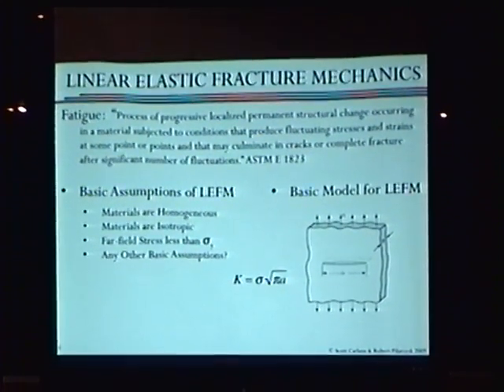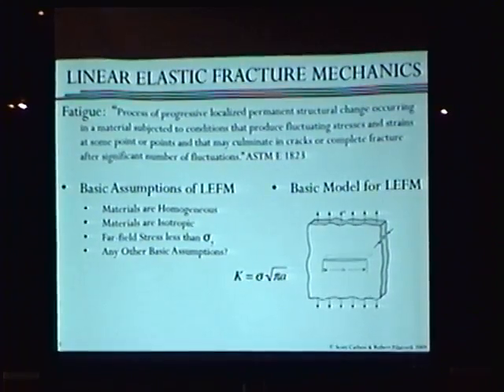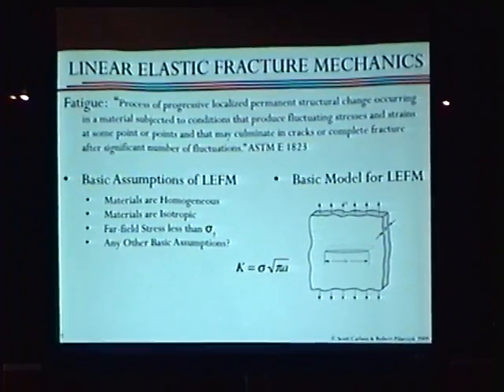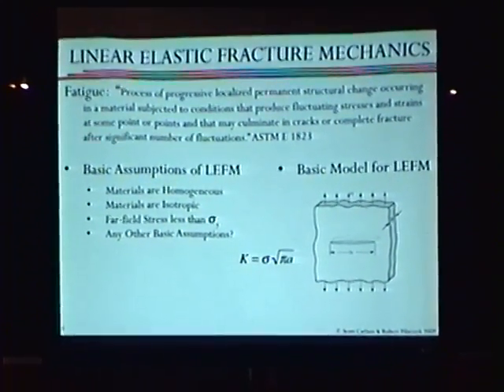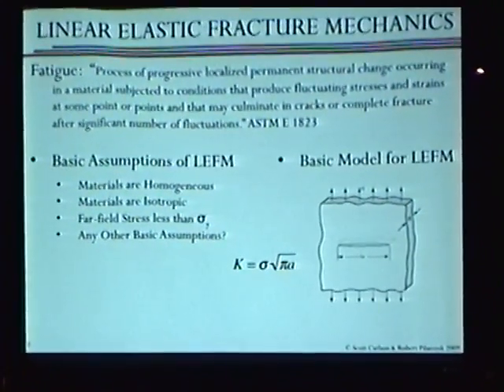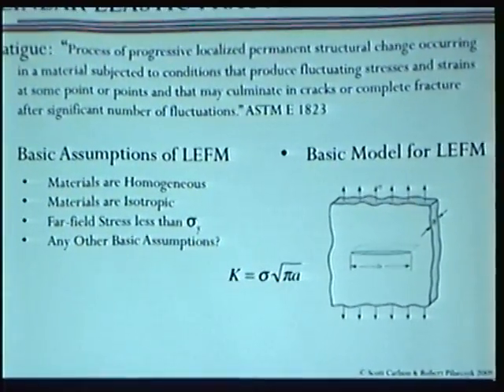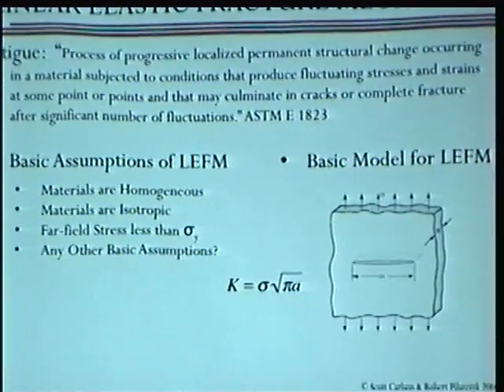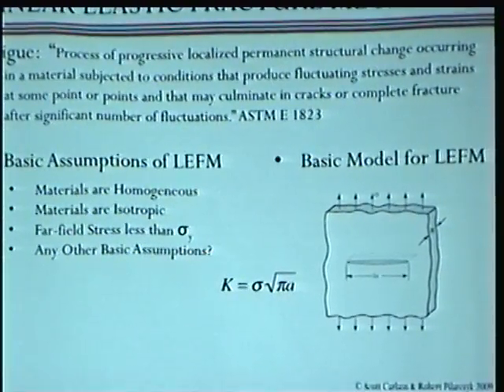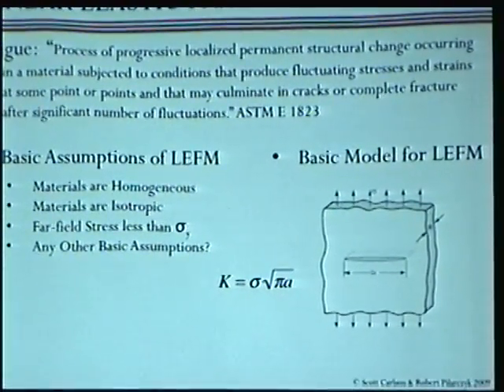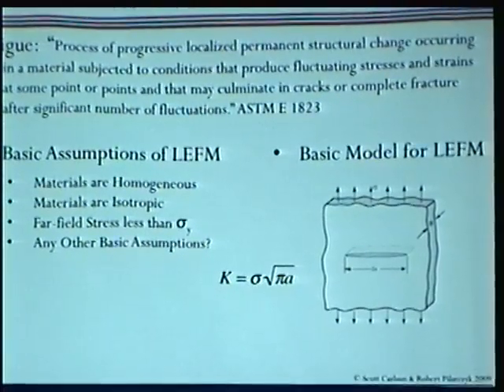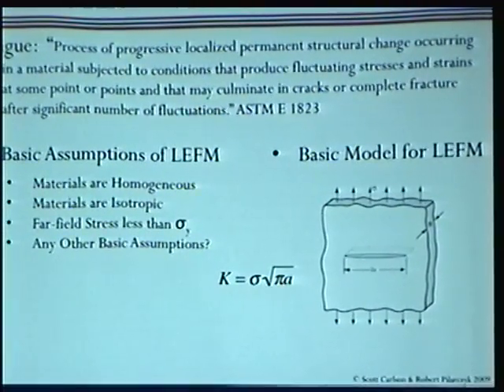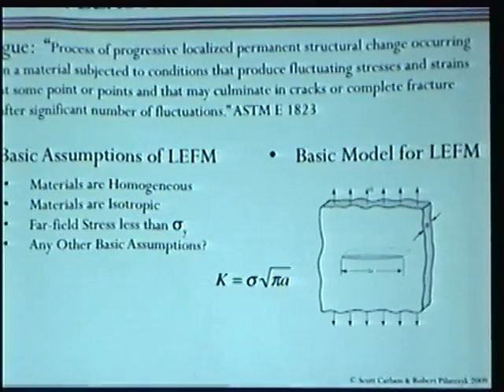I'm not a fluids guy. I don't like partial differential equations. I like simple algebra. And this equation is pretty simple. It solves for something that's called a stress intensity. That stress intensity is a local property at the crack tip that correlates the far field stress and the crack size to determine if that given component will fail or not.